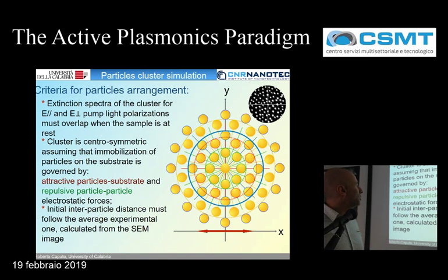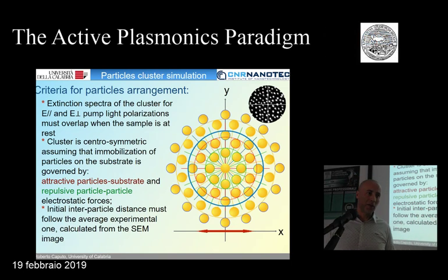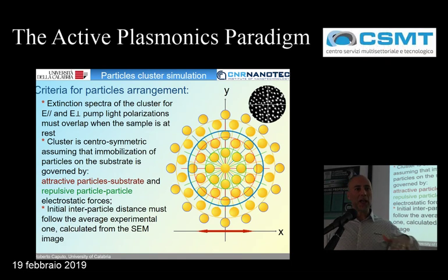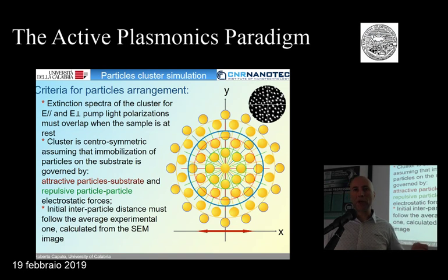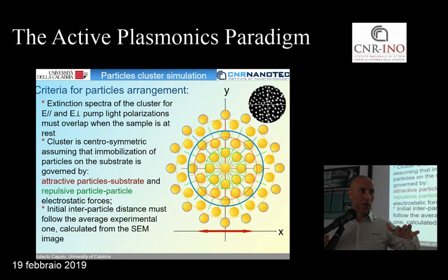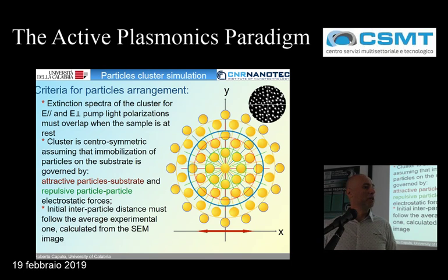Then, of course, we wanted to keep the average distance in a reasonable way with respect to the real case, and we considered that the realization of this sample in an experimental way is due to a kind of electrostatic problem, because we functionalize the surface and it acquires a given charge, and the particles themselves are charged but with opposite sign, so they tend to go away from each other during the deposition, but at the same time they are attracted by the substrate. So this is not exactly a random distribution of particles if you think about that, because we have kind of electrostatic interaction that generates the result.